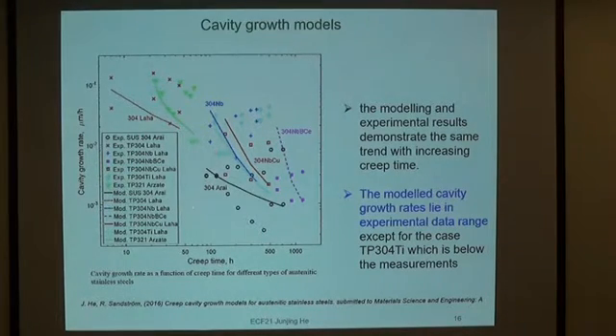Here we show the results for the modified constraint cavity growth models. So these are the results of the new models. And here is the cavity growth rate as a function of creep time. Both the modeling and the experimental results demonstrated the same trend with increasing creep time. Also, the modeled cavity growth rate, the lines, lies in the same range as the experimental data.